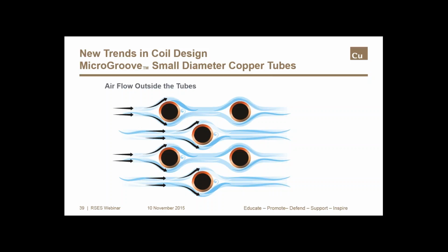Just as we saw with microgrooves inside of the tubes, outside, the tubes break up any boundary layers that the air tends to form as it flows through the coil. The more tubes we use, the more we break up the boundary layer on the air side, and the more heat transfer we'll get. But in many cases, more tubes also means a higher air side pressure drop. So there's a balance at some point where a coil uses an optimal amount of air to achieve the heat transfer that the system requires. Remember also that heat's being dissipated by the fins, and the fins have slots or louvers, again to break up boundary layers and improve heat transfer.